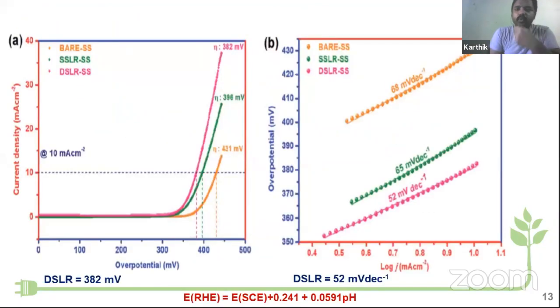This slide shows the OER, oxygen evolution reaction, of the as fabricated electrodes. Figure A is the linear sweep voltammetry curves of bare, single side and double side laser rusted stainless steel. So it's one kind of fuel cell reaction, as Dr. Gaudaman said in the earlier presentation. The minimum output is about 10 milliampere, and all three electrodes achieved that. But among these three, the double side laser rusted stainless steel achieved a very low overpotential of about 382 millivolt.